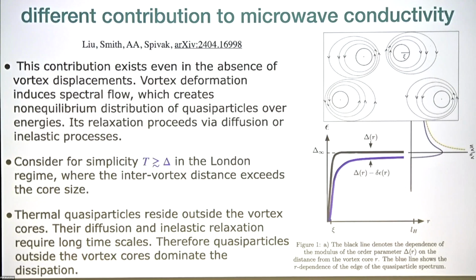Okay, so the contribution I'm going to discuss exists even at perfect pinning, where vortices are not displaced and this friction plays no role. And the dissipation here arises because the distribution of the superfluid momentum outside the cores is disturbed by the microwave field, and this causes spectral flow, a non-equilibrium population of quasi-particles in energy, and this distribution relaxes either via diffusion of quasi-particles across long distances on the order of the intervortex spacing, or by inelastic relaxation.